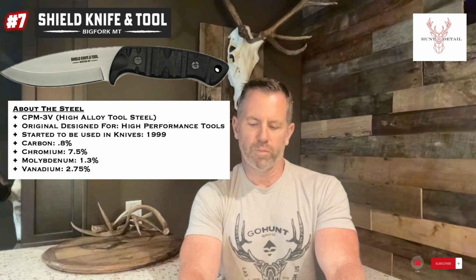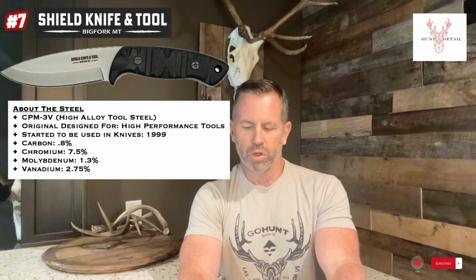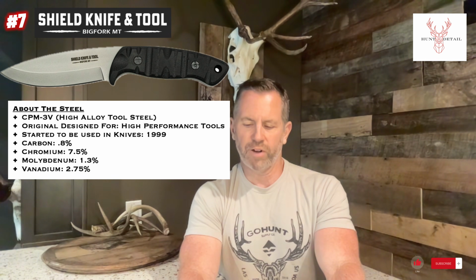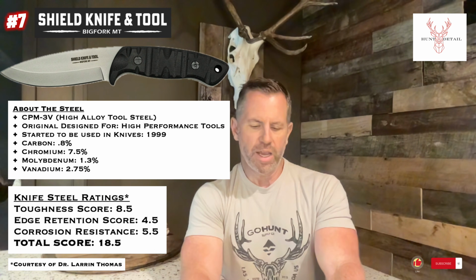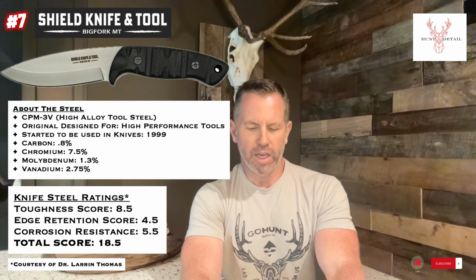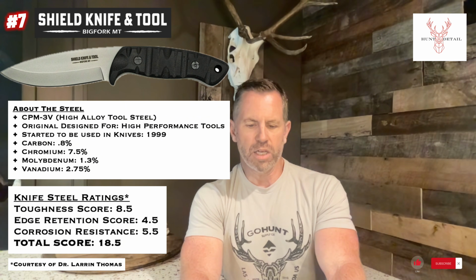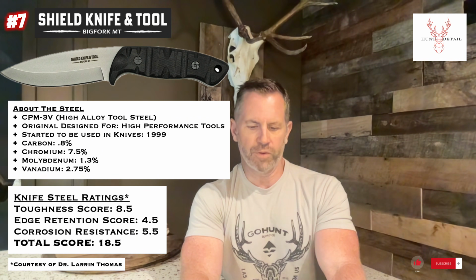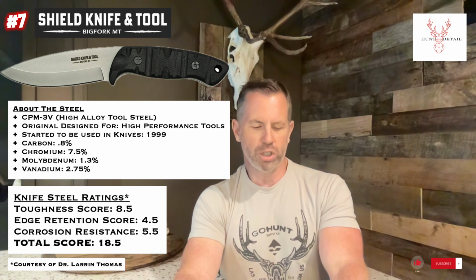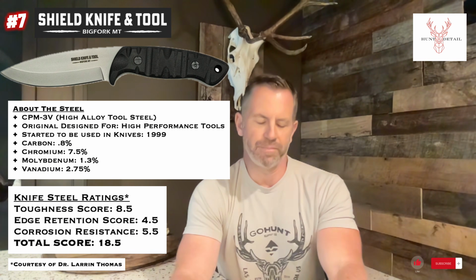So you have 0.8% carbon, 7.5% chromium, 2.75% vanadium. And from a scoring standpoint, it scored very high from a toughness at 8.5, the edge retention at 4.5, and the corrosion resistance at 5.5, for a total score of 18.5 for the Shield Knife and Tool, Bigfork, Montana.